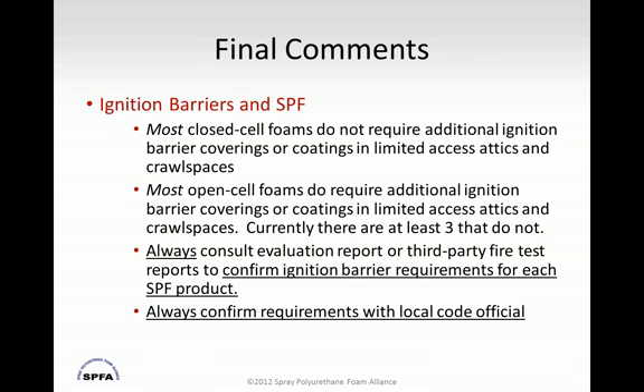As for ignition barriers, I can probably make some general comments here. Most closed-cell foams do not require an ignition barrier coating or covering in these limited access attics and crawl spaces. Most closed-cell foams have actually passed the Appendix X test, which means it lasts 4 minutes and 18 seconds with a 40 kilowatt burner fire, which makes it equivalent to foam with 1/4-inch plywood over it. It passed without any additional covering.